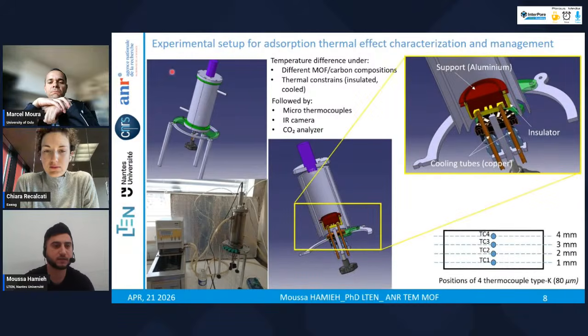So after understanding the impact of thermal effects and how we aim to address them, we first need to quantify these effects experimentally. Because of that, we developed the following experimental setup. This is a double envelope stainless steel cylinder, which allows circulating cooling water from a thermostat bath to control the temperature of the cylinder. Here at the top, we have an infrared camera to monitor the surface temperature of the sample. The material is placed on an aluminum support, which includes, under this support, a heating resistance for controlled heating, as well as cooling tubes.